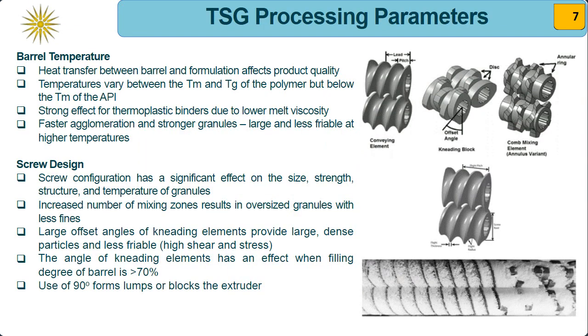Twin screw granulation processing is controlled by a variety of processing parameters, and some of them are listed below. So the very first one is the barrel temperature. We know that the heat transfer between the barrel and the formulation affects the product quality, and usually we use temperatures that vary between the melting point or the glass transition of the polymer, but usually below the melting point of the API. There's a strong effect of thermoplastic binders due to low melt viscosity, and it has been found that by applying higher temperatures, we have faster agglomeration and stronger granules, which have large size and are less friable.